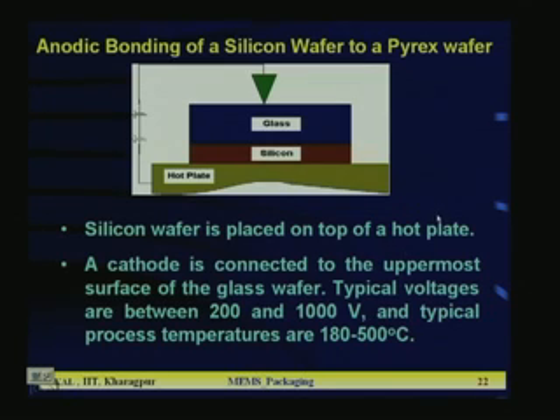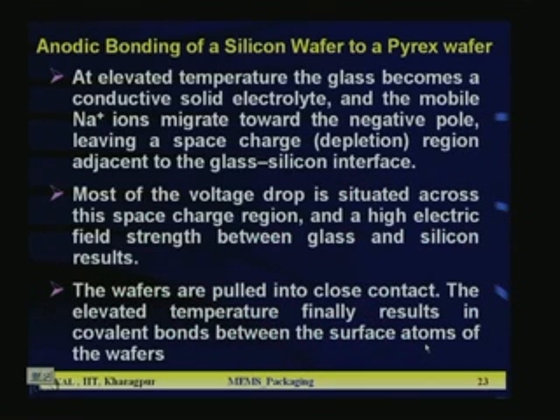So, the silicon wafer is placed on the hot plate, and a cathode is connected to the uppermost surface of the glass wafer. Typical voltages are between 200 to 1000 volt, and you have to calibrate the whole system depending on your requirement, how much bond strength you need, and typical process temperature is 180 to 500 degrees C. Here again some things are elaborated regarding the bonding mechanism. At elevated temperature, the glass becomes a conducting solid electrolyte. Since sodium ions migrate towards the negative cathode, the glass wafer used at the top as a cathode must be a little bit conducting, otherwise the formation of the depletion layer will not be possible.